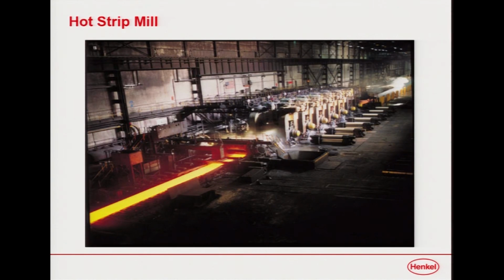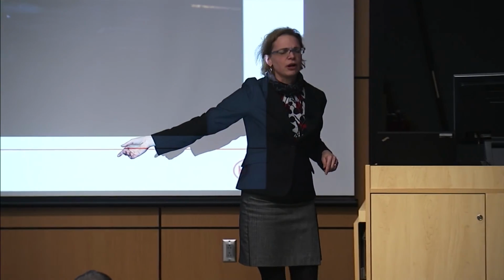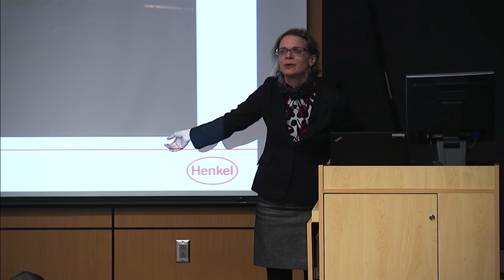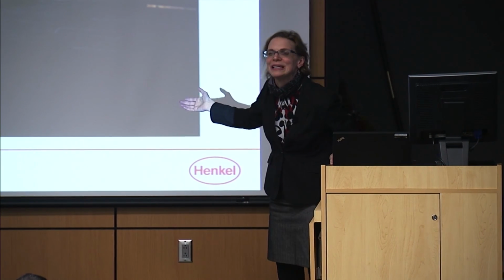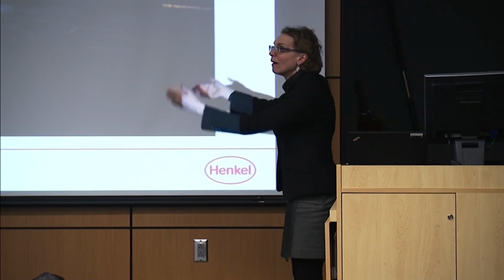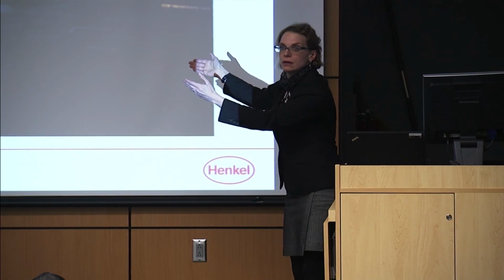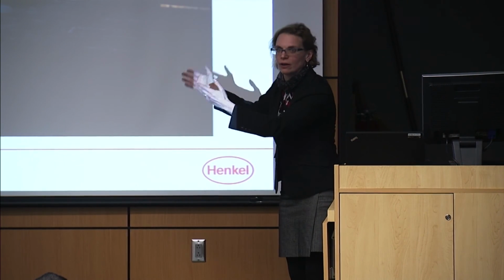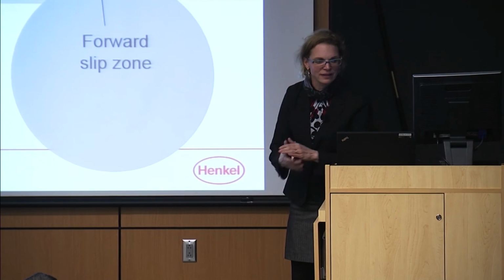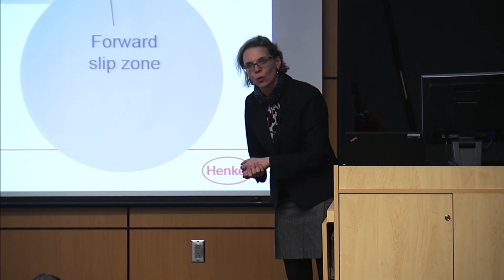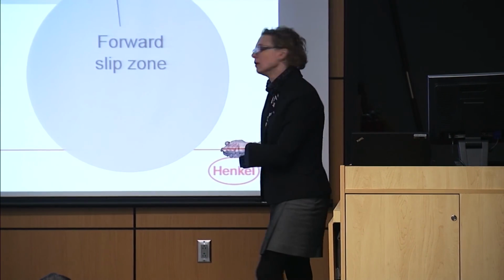In this case, the steel is yellow, so it's about, I think, around 2,000 F. It's very, very hot. It's a very challenging chemical condition, you can imagine. Remember we said we needed heat to drive chemical reactions? Well, there's your heat. We don't need a whole lot of friction here. In fact, in the rolling contact, we don't really want a whole lot of friction at all.